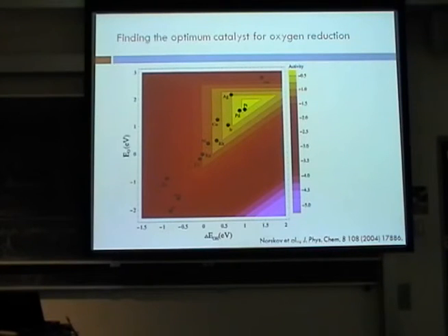All right, how are we going to make the situation better? How are we going to design a catalyst that is either better than platinum, that would be ideal, or at least that uses a lot less platinum or uses a less expensive material than platinum? Because we can use platinum to get very good power densities in fuel cells, but you just have to use a whole lot of it. And so there was a number, I think it's improved, but a few years ago, that if you equipped 20% of the United States vehicle fleet with hydrogen fuel cells, it would use up all the platinum in the world, including what's already in our catalytic converters, for example. All right, so we clearly have to find a way to use less expensive materials or use a lot less platinum.